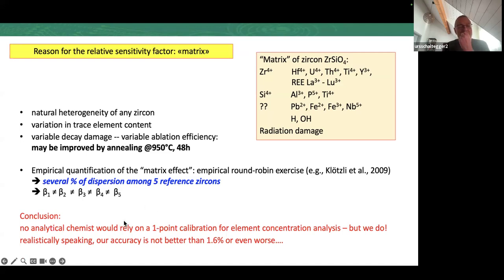So what is the conclusion out of this? No single analytical chemist in the world would rely on a 1-point calibration for element concentration analysis. You know, XY, you have at least 3 points, you make your calibration curve. But we think that with 1 it's fine. So realistically speaking, our accuracy is definitely not better than 1.6%, but could even be worse.